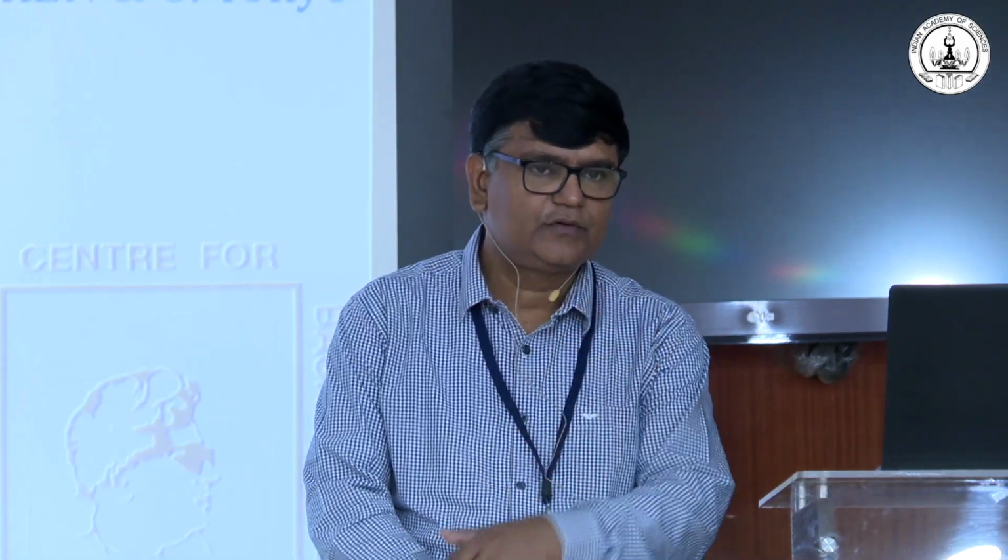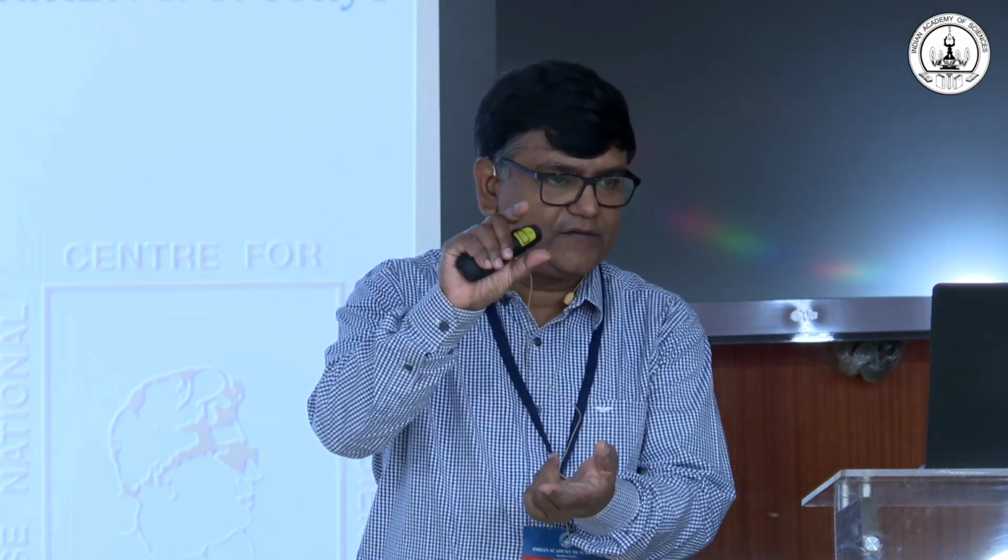I have one simple question. You have shown nine domain patterns over there for several samples, like stripe-like and then bubble-like and all. So the domain wall thickness you mentioned is between 100 nanometer to 200 nanometer. Yes, something like that. So what should be the thickness of that top layer where you have measured this? You mean the cobalt layer? Yes. That is less than a nanometer. The width of the domain wall is 100 nanometer. This is a lateral width. And the thickness in the z direction is a little less than a nanometer.